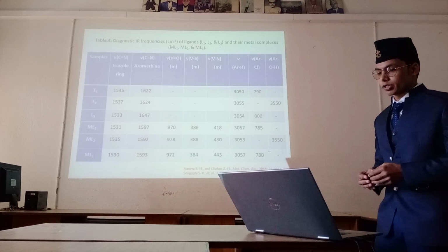The spectral band at 980 to 970 per cm is found in all synthesized oxovanadium(IV) complexes, which is due to the vanadium to oxygen stretching. It is the main strong evidence for the formation of the oxovanadium(IV) complexes.